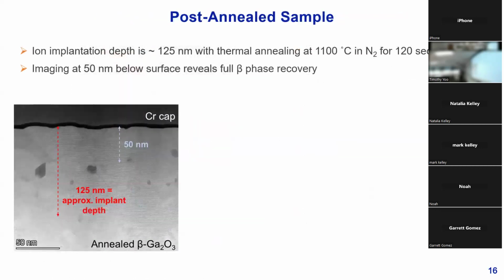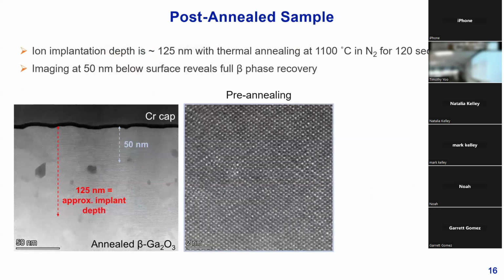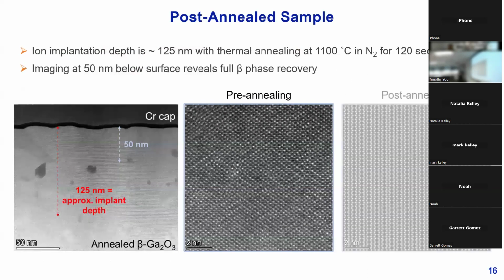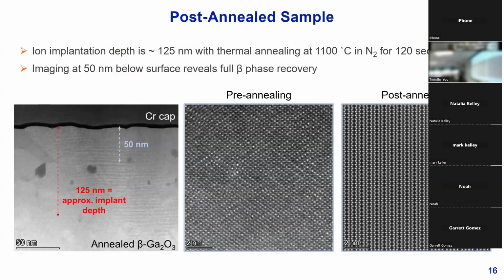And so with that, we sort of covered everything that we found with the as-implanted film, and now we can move towards the annealed part of this film and see how well the annealing parameters recovered the structure. So here, rapid thermal annealing was done at 1100 Celsius in a nitrogen environment for about 2 minutes. And so first, about 50 nanometers below the surface, if we compare a before and after image, we can see that the ideal beta phase structure is indeed fully recovered after annealing.